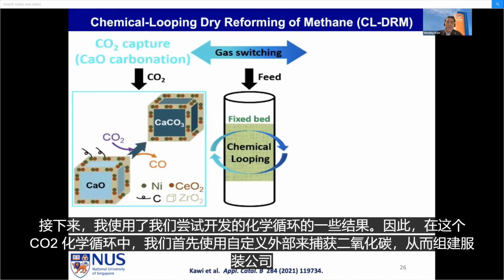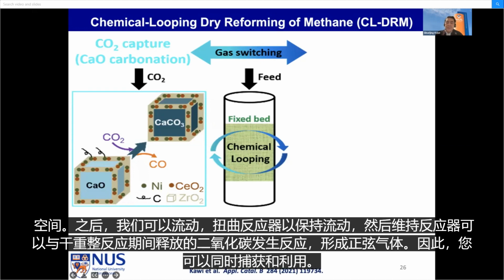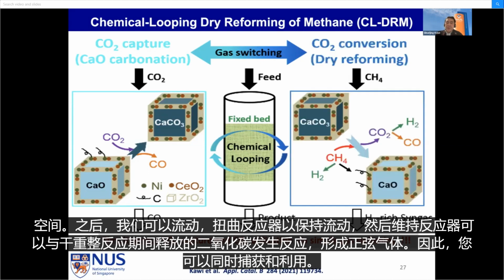So in this CO2 chemical looping, we use calcium oxide to capture the CO2 to form calcium carbonate in the first phase. After that, we can then switch the reactors to flow methane, and the methane can then react with the CO2 that is released for dry reforming reactions to form syngas. So this is the simultaneous CO2 capture and utilization.